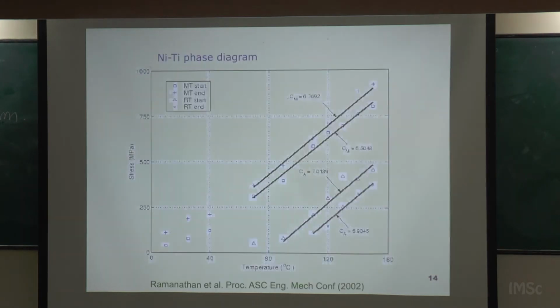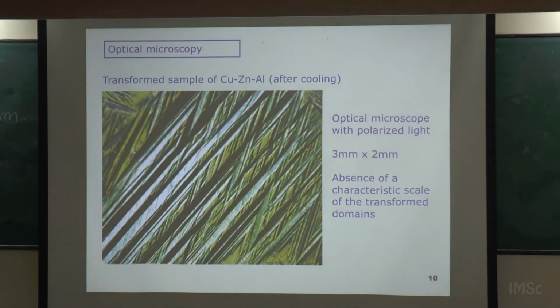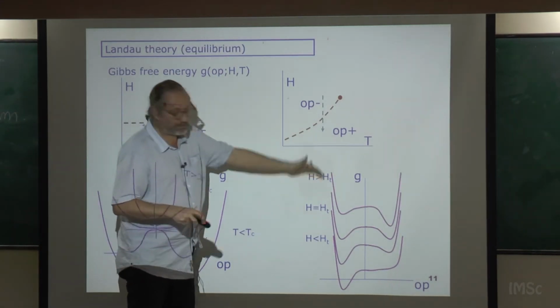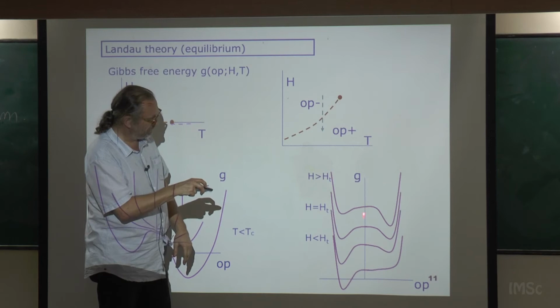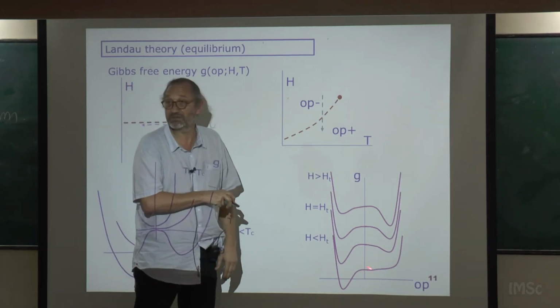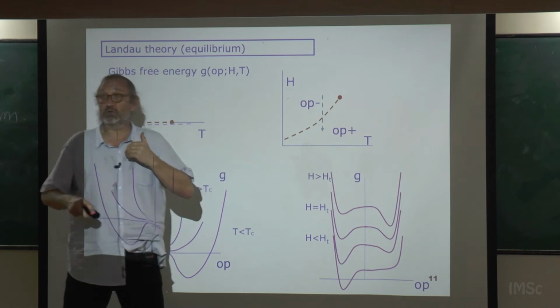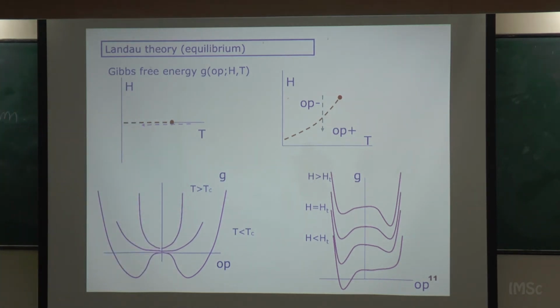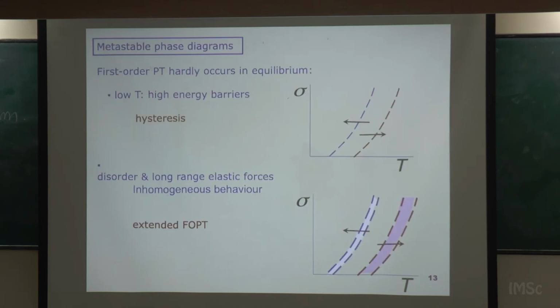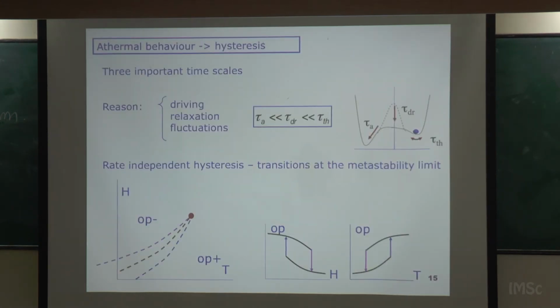If I go back here, what I do when I drive with an external field is to make this barrier smaller and smaller until it disappears. I can do this faster or slower, and this is the typical time for driving. So we have these three time scales. When do we expect hysteresis? We expect hysteresis when this limit here is fulfilled. It's clear that the time for the relaxation is going to be very fast.